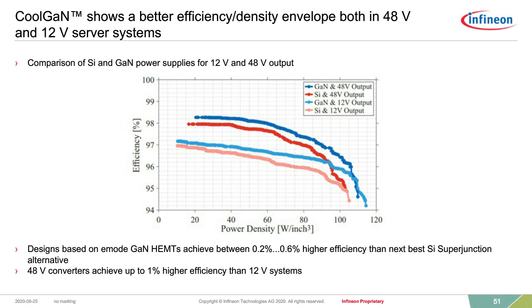Here we are comparing not one-to-one, but we are comparing silicon in its best use case, which means more complex control. So totem pole, for example, in triangular current mode modulation, which eliminates the hard commutation, which achieves zero voltage switching for the CoolMOS. So you pay basically in silicon with more complex control and interleaving of phases on a topology side. If you go with GaN, the topic becomes simpler, the control is straightforward, but you see that silicon is not that far off.